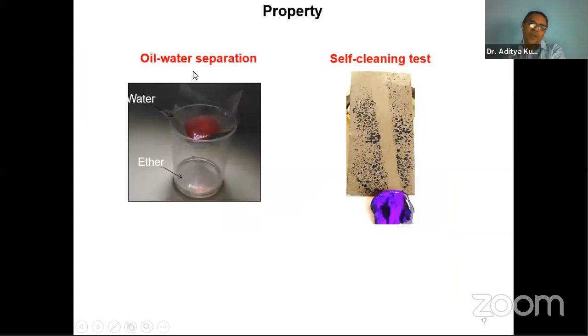Self-cleaning I already described to you. Next, oil-water separation. If you tune the wettability in that way, you can have one liquid repelled and one not. Take an example. Here, this is a metallic mesh. We tune the surface so that it is super hydrophobic but super oleophilic, meaning it likes oil to pass through it, but it does not like water passing. So water is repelled by this surface, and oil passes through. So if you have an oil and water mixture and you just pour it onto the surface, because of gravity, you can easily separate the oil from the water.